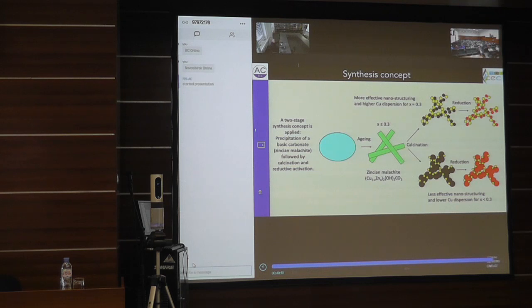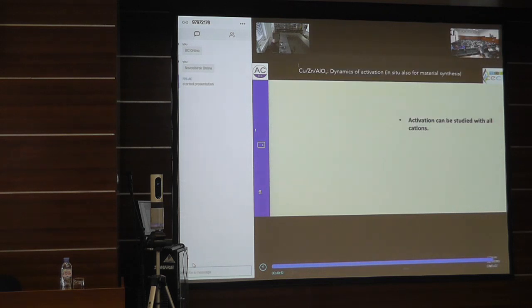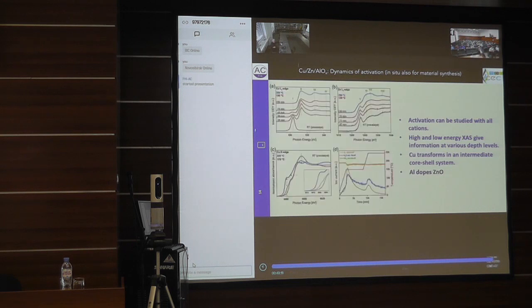So, how do we generate this catalyst? Again, this is useful to do in operando spectroscopy. And what I show you here is that this reduction of the material is happening in two stages. And that is the reason why you generate not brass as a product of this. You would think copper oxide and zinc oxide reduced with hydrogen gives you brass and water. And of course, fortunately, this is not the case. When you do this in the lab, under normal conditions, you get this.